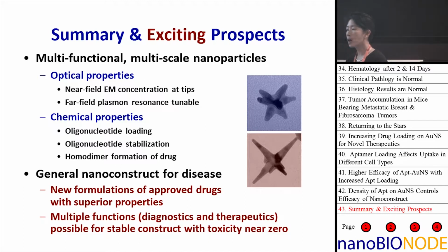So adjusting how you do the chemistry at the different pH based on the pK of the buffer, that helps. So you can get things that look like this or this. You can also change the relative ratios of the gold starting precursor as well as the buffer. And then we have found that we can tune over the entire visible and near infrared range. So there's ways to do that there.